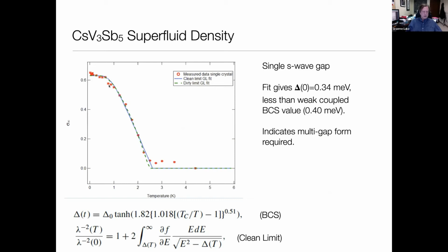So these are the data points, and then we can fit the temperature dependence of this to various models. The first thing we see is that if we try to fit this to just a standard weak coupled BCS temperature dependence, it doesn't work. So what we use is a more general form. From BCS theory, we know what the temperature dependence of the gap is in terms of the reduced temperature T over TC here. This is just a result of BCS theory.